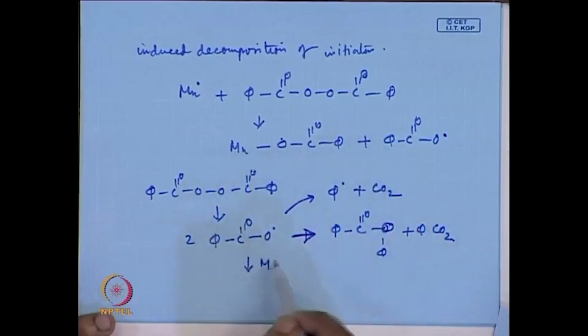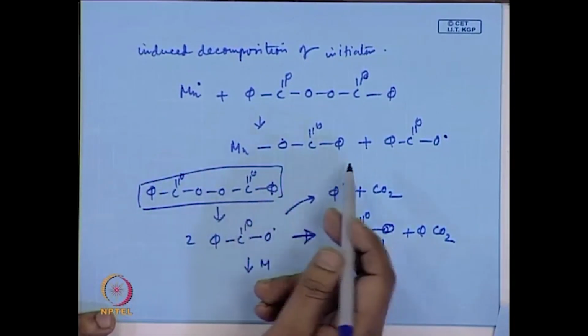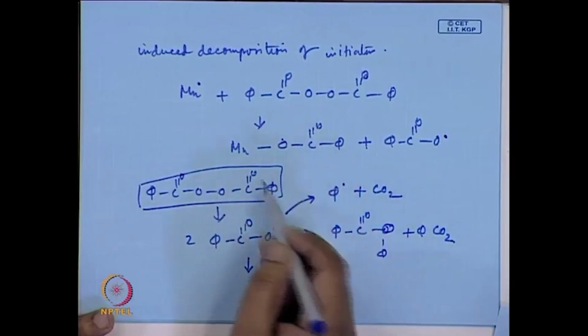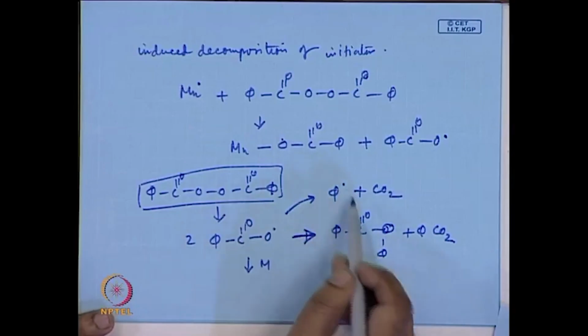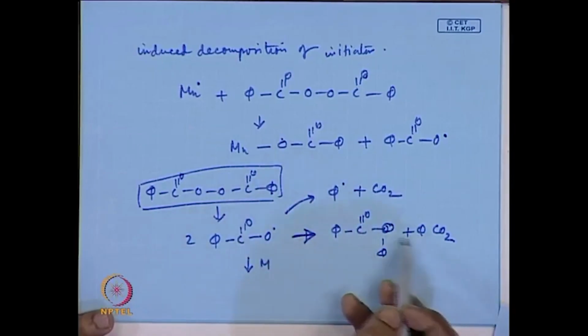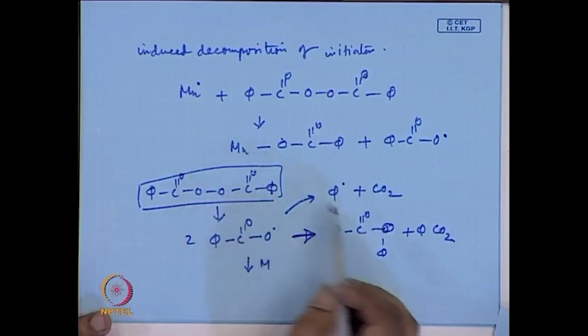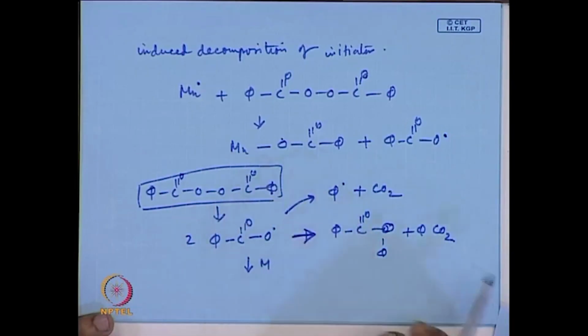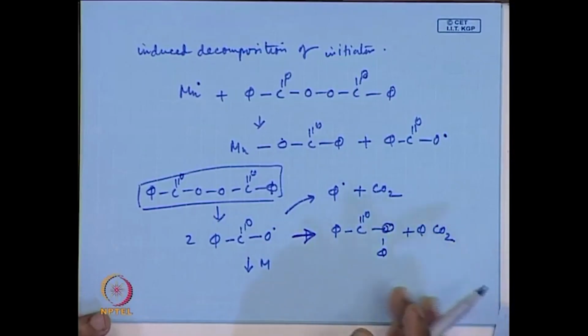So, if there was no side reaction, the amount of radicals generated would be higher, but now it has reduced because of so many side reactions. In other words, all the radicals which are getting generated by homolytic cleavage of this benzoyl peroxide are not initiating a chain, which means they are getting lost in non-polymerization reactions.